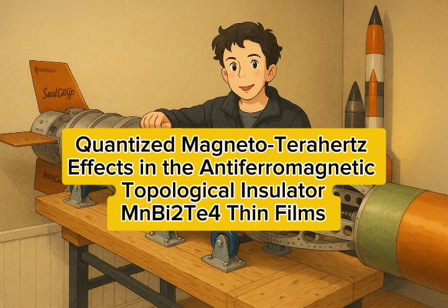Extremely suggestive, yes. What about the Kerr rotation, the reflection? Did it follow a similar pattern? Broadly, yes. For the 6SL film, Kerr rotation was 0 at 0 field, again, as expected for the AFM state. As they increased the field, a Kerr signal appeared. Interestingly, it showed frequency dependence. It was generally larger at lower terahertz frequencies. And at the highest field, 6 Tesla, it reached its maximum value, around 8.5 milliradians at the lowest frequencies measured.